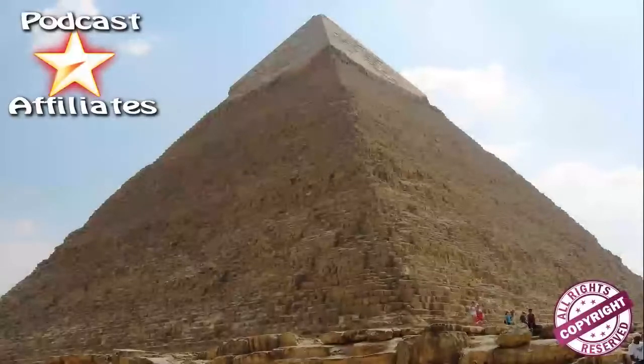30 years ago, an American team scanned the different pyramids with their radars, trying to find hidden chambers, and they measured the humidity of the stones, and they found 8.59% of water in the pyramid stones, whereas the genuine limestone from the bedrock in the vicinity contains 1 or 2% by weight maximum. So this is something that is very interesting.